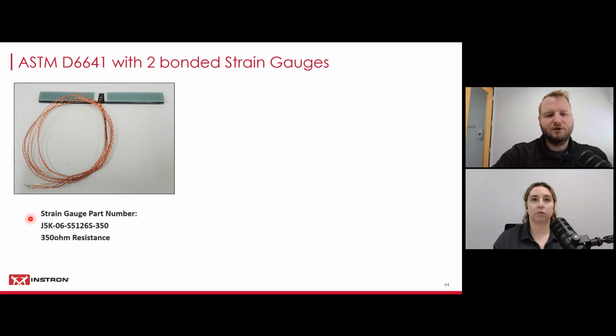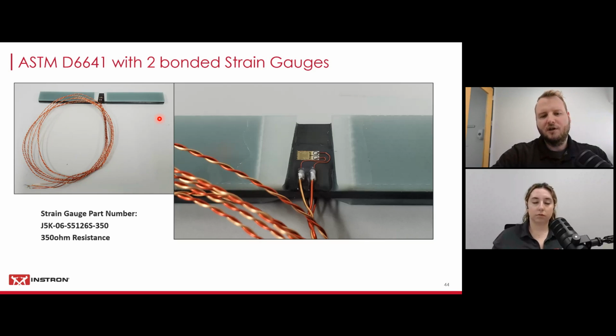You can see the strain gauge part number down here, and it's a 350 ohm resistance, which is actually recommended in multiple testing standards. So if you're wondering if you should use 120 or 350 ohm, which seem to be the most popular versions out there, 350 ohm I have seen being recommended in the testing standards. And here's a nice close-up picture of the strain gauge bonded to the specimen, and you can see the cables here coming from the underside where the other strain gauge is bonded to the specimen.